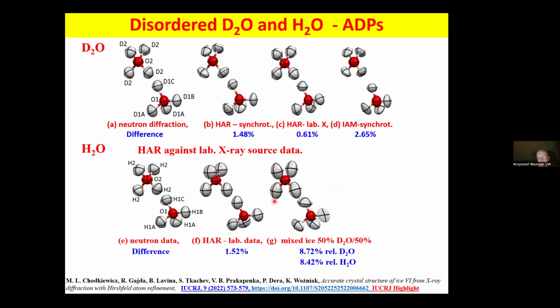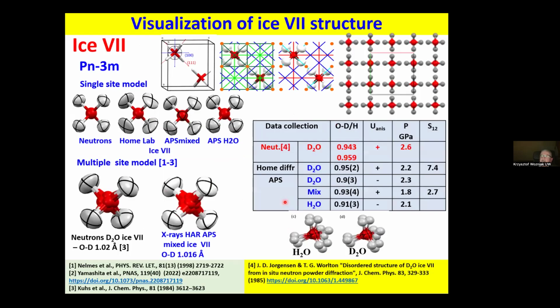And of course, for mixed ice, we have a far bigger difference because we have 2 different sources of errors, as we have only 50% of one moiety and 50% of the other, and they have different thermal motions. So we are having those errors at the level of close to 9% when we compare them with atomic displacement parameters obtained for pure D2O ice or H2O ice.